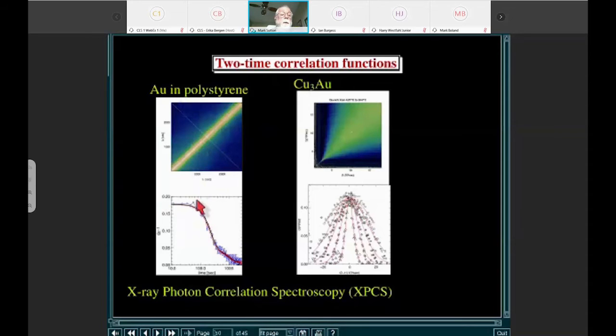But if in equilibrium, we can average over all of these. They're all different measurements, and so then we can get the red line, and that's basically by averaging, and that's what we would do for equilibrium or steady-state systems. As a matter of fact, we use a sophisticated algorithm, and we get the black line that you may or may not be able to see. It's called the multi-tau algorithm, which basically optimizes the signal to noise.